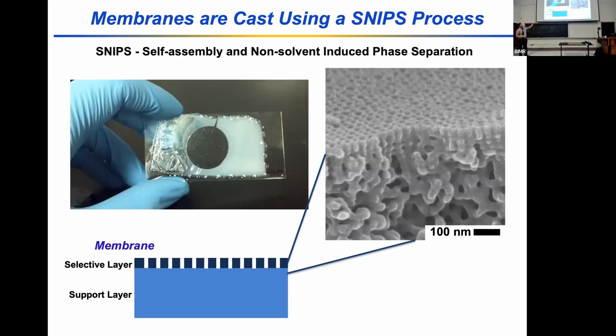And when we drill down on the cross-sectional morphology right at the selective layer-support layer interface, you see these hexagonally packed cylinders percolating from the top surface of the membrane down into the support layer to create this ideal filter.